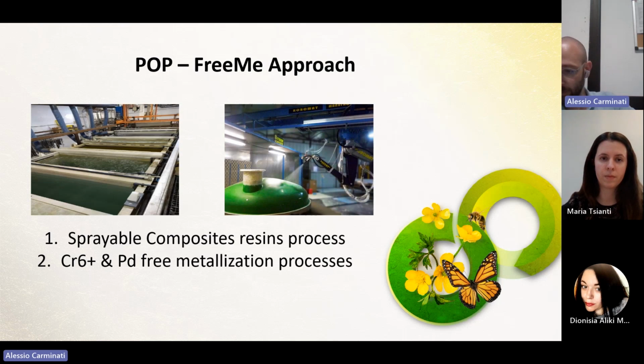On the other hand, we have a different approach that involves the use of other chemicals, but the same type of plant currently used. So basically, in this kind of approach, the chromium and the palladium are substituted by more environmentally friendly chemicals like some peroxide, of course, not every kind of peroxide, and some other colloidal particles that are able to activate the metal, typically nickel particles from some precursor.